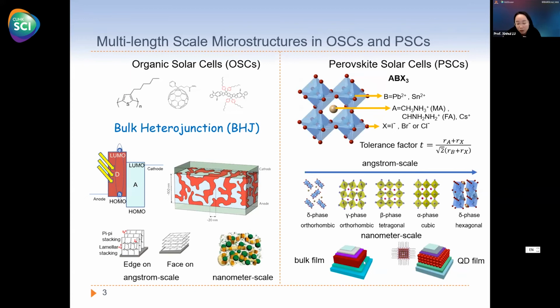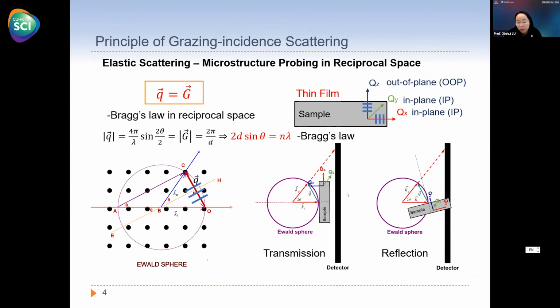And then going to a little bit larger scale, the grain size in the bulk film, or if the active layer is formed by quantum dots, perovskite quantum dots, how do the quantum dots pack? These kinds of nanometer scale structure will also affect the device performance. So to probe this kind of microstructure, we are using grazing incidence scattering. Basically, we are making use of this scattering wave vector Q as a probe to probe the 3D ordered structure inside this thin film. So this Q should be aligned to the normal direction of the ordered structure. Then we can probe that structure.